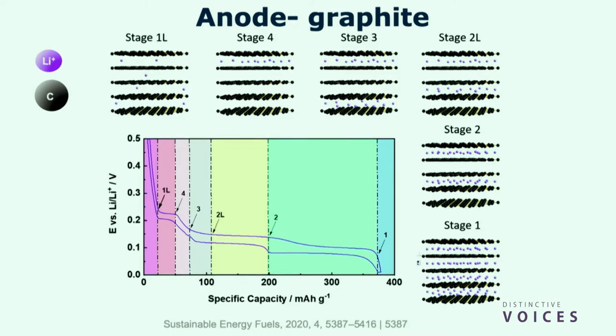So stage four is every fourth basal layer of graphene in the graphite filled by lithium, right? So this would be stage four. Stage three, every three layers, lithium. Stage two, every two layers, until you get a fully saturated stage one. All of the graphite is intercalated with lithium, and that's where it's basically full, right? So that's what happens physically when we put lithium into our graphite anode. And then the opposite happens when we take lithium out, right? You get the destaging of lithium and graphite.